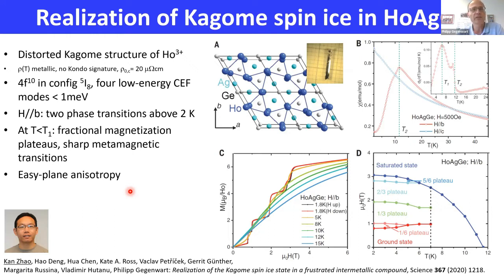Holmium in the 3+ state is a non-Kramers ion. It has 10 f electrons, and the total spin orbit coupled moment undergoes the crystal electric field splitting. And in fact, here we have 4 low energy crystal field modes, which are all within 1 milli-electron volt, which is smaller than the RKKY exchange magnetic coupling, because you see that the magnetic ordering happens at 12 Kelvin, which corresponds to about 1 milli-electron volt.